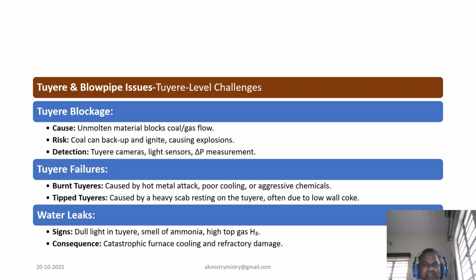Now, down to the business end, the tuyeres. This is where the action happens and where failures are most dramatic. Blockages from the unmolten material can cause coal to back up and ignite, leading to explosion. This is why tuyere cameras and pressure sensors are critical. Tuyeres themselves can fail, burning out from the hot metal attack or tipping from the weight of a scab above.